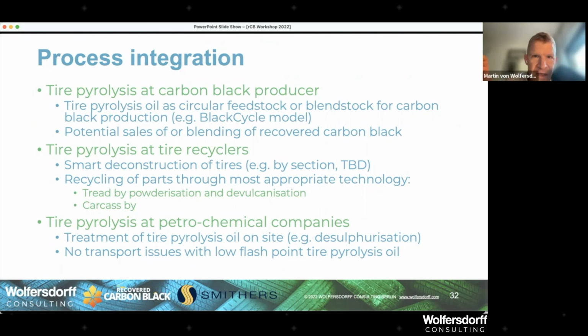But for me, the hierarchy would be, if you have a pure material like the inner liner or tubes, that would go into devulcanization. And the pyrolysis really is the most forgiving tire recycling process, which accepts textiles and steel. And the carcass, if you can't separate really the carcass and the plies, it would make sense to go in the pyrolysis. And so that's what I'm indicating here. Tread could be powdered and devulcanized, and then, carcass is missing pyrolysis. Carcass could be recycled by pyrolysis. That's the missing word here.